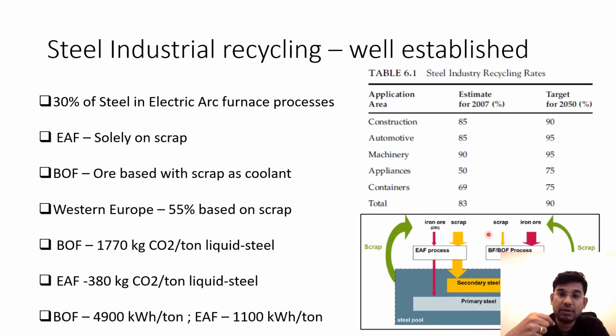And in EAF, sometimes you also have usage of DRI, direct reduced iron, from which steel is made. See, for the traditional BOF route, you have 1,770 kg of carbon dioxide per ton of liquid steel, whereas for the electric arc furnace route, that is the secondary production, you have substantially less CO2 emitted per ton of liquid steel. The same for the BOF in terms of energy consumption. It's 4,900 kilowatt-hour per ton, whereas for EAF, it's quite less. It's just 1,100 kilowatt-hour per ton. So you have a very well-established recycling process with very well-defined savings in energy as well as in emissions.